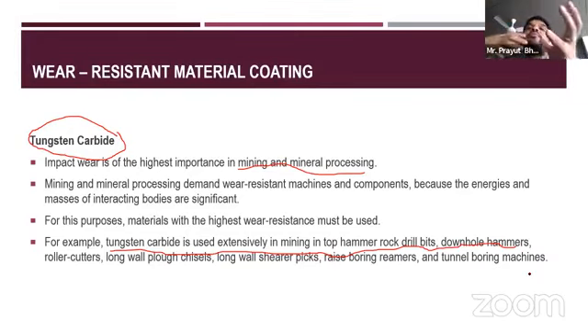So where sand itself, as we saw, has a hardness of about 8-9, it's a very hard material and a very abrasive material. So when applying tungsten carbide to the component, it will come in contact with the sand, this abrasive material, and protect the main component from coming in contact with the sand, taking all the abrasion by itself. It will fight against the abrasion.